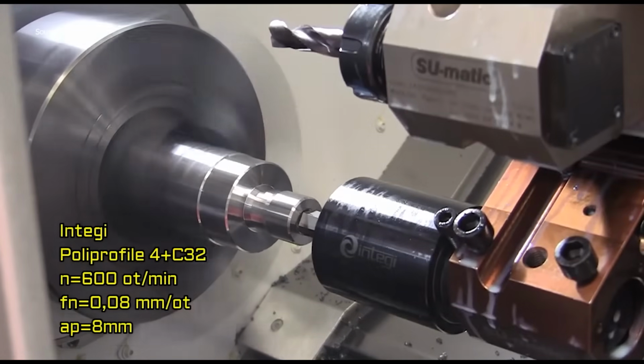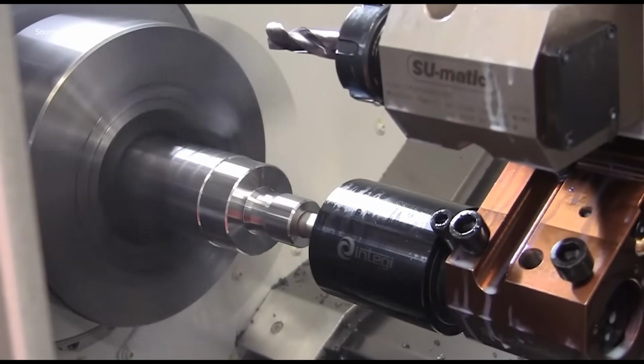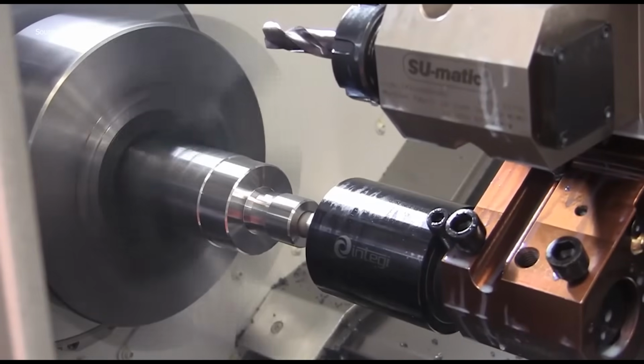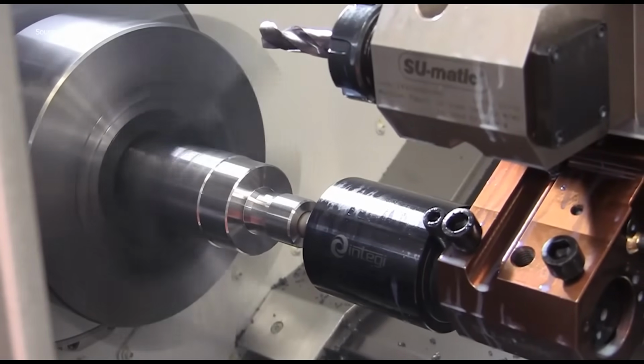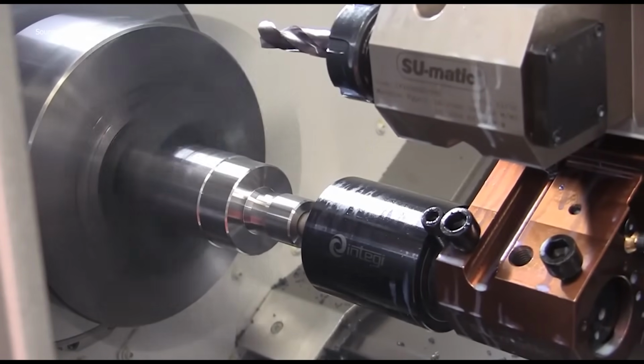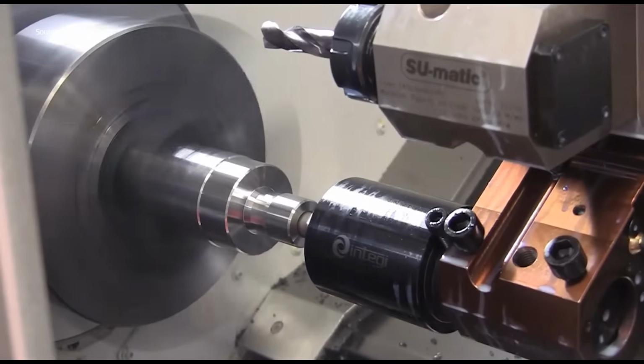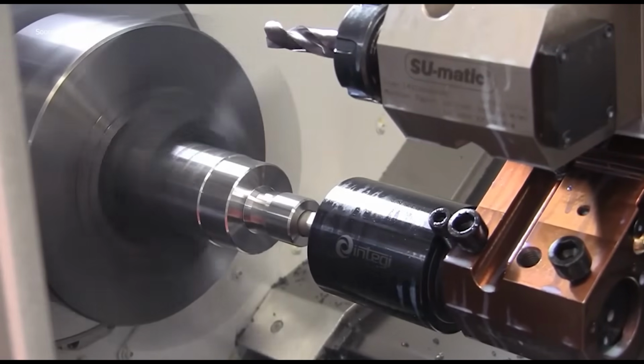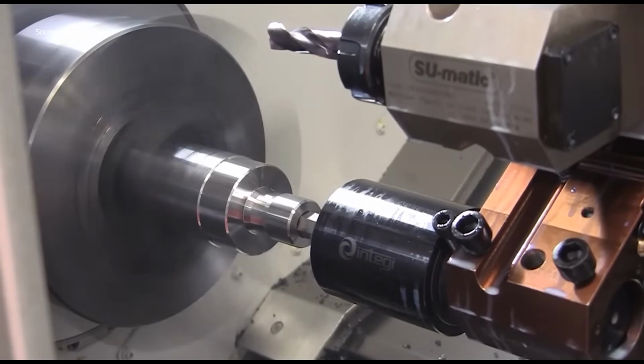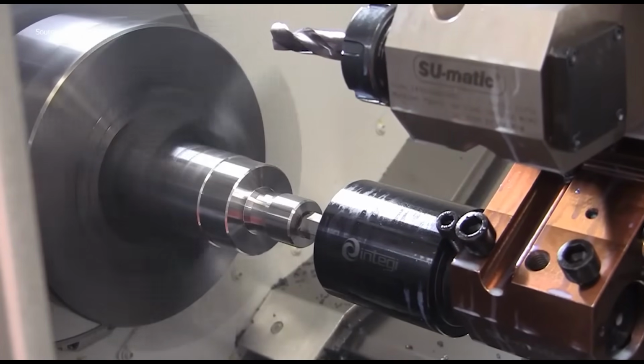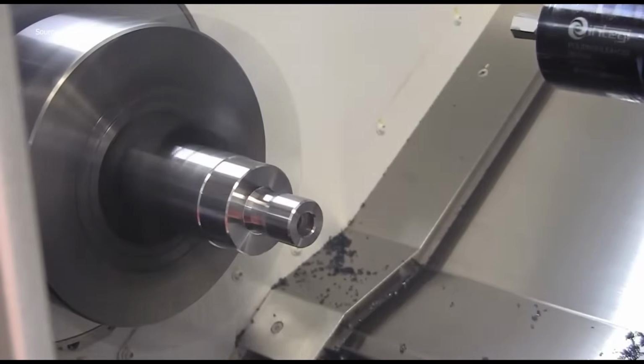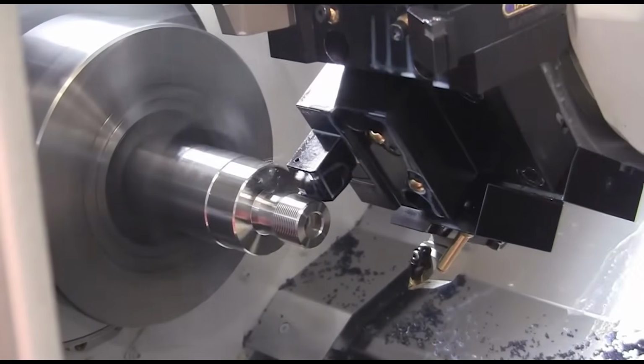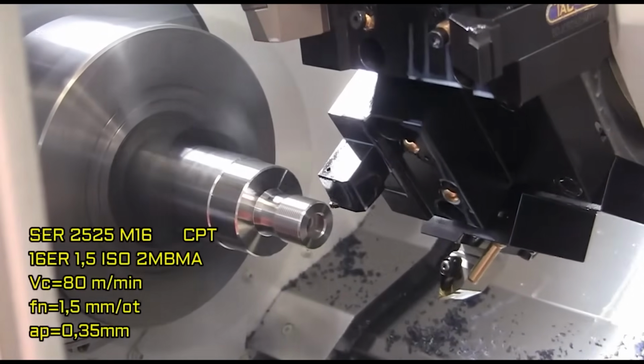From profiles to grooves, the level of control is razor sharp. A contouring pass follows, using a polycrystalline insert to maintain surface integrity at high cutting speeds. The Y-axis comes into play for offset milling, making angled cuts impossible on simpler lathes. Drilling is fast and steady, driven by a synchronized turret that aligns each motion perfectly.